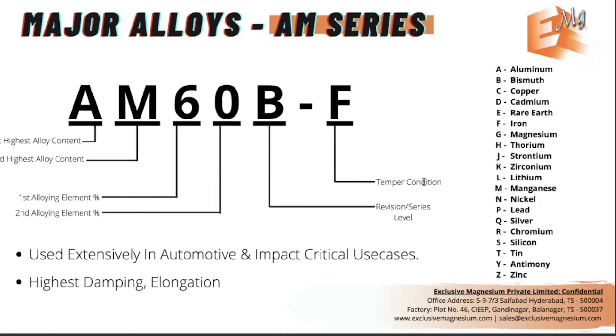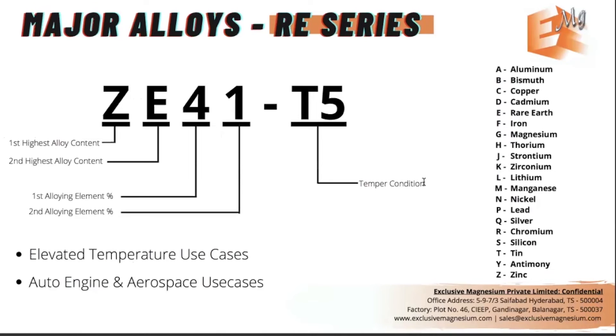The AM series also has very high elongation, making it suitable for alloy wheels. The third major series used globally in magnesium are the ZE series — the rare earth series — where 'Z' is zinc and 'E' stands for rare earth elements. The reason this alloy is heavily used is that other magnesium alloys have lower creep resistance at elevated temperatures, making them unsuitable for engine applications. The ZE rare earth series is used specifically for auto engines and aerospace use cases subjected to elevated temperatures, maintaining good strength even between 200 and 350 degrees Celsius.